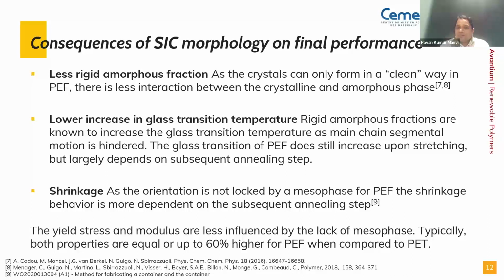And the glass transition of PEF does still increase upon the stretching, because there is a very clean amorphous region. So when the filaments or the polymer chains are again drawn, then the amorphous region is more oriented again, and the glass transition temperature can be increased. But we also have to always keep in mind that these are theoretical things. We know these impacts are very prominent, but there is always a combination of drawing, annealing and heat setting, which decides what will be the final values of the transition temperature.